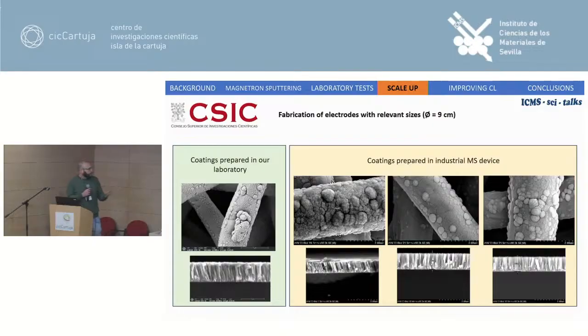So we can now obtain a big amount of electrodes with this chamber. If we compare the structure of the catalytic coating deposited in our laboratory with those obtained in this chamber, here we have 3 examples of 3 different electrodes, and here is our electrode deposited here. We can see how the columnar structure remains in both the laboratory and the scale-up chamber, and the structure of the catalytic layer over the fibers is quite similar, with these agglomerates and this mesoporous structure that I described before.